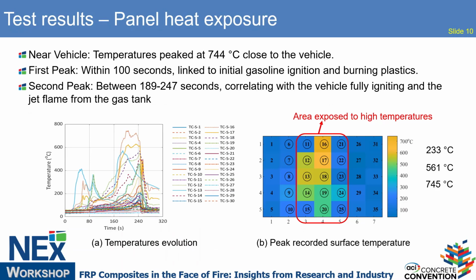So this is the temperature we measured over the surface of the overlay. The peak temperature we measured is 744 degrees Celsius, close to the vehicle, and this is because the liquid gasoline is directly burning over the surface, which gives the high peak temperature. And in the test, we measured two peak temperatures.